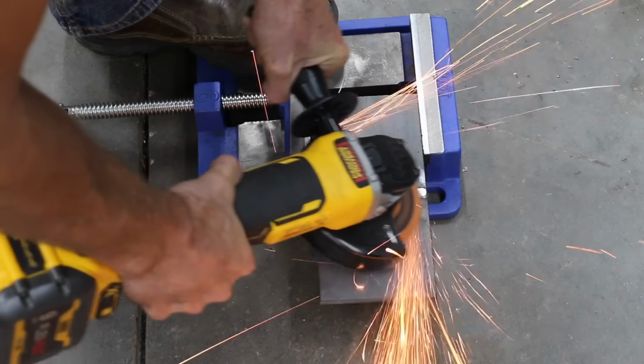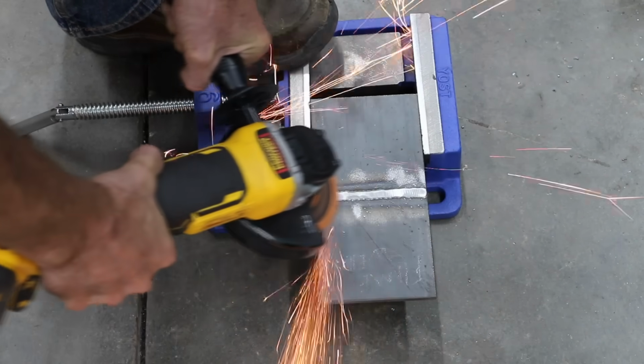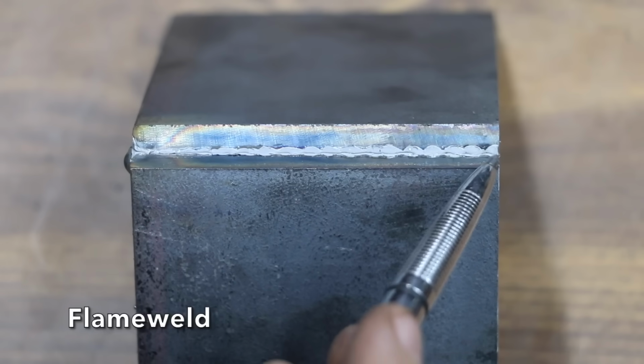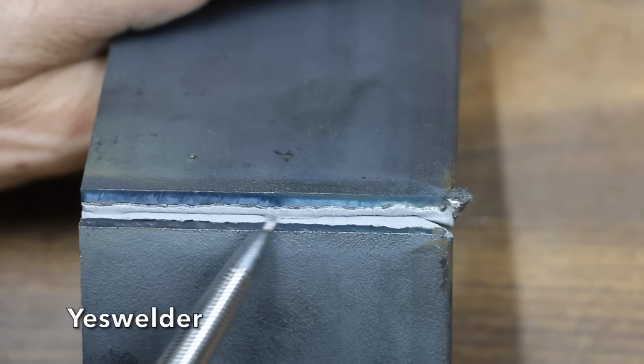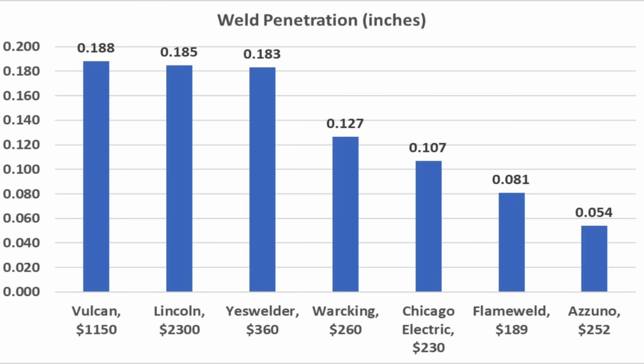I'll go ahead and grind off the weld that's just above the steel plate so we can measure penetration. I folded each of the test pieces and measured the area with the deepest penetration for each of the brands. And the Vulcan delivered the deepest weld at 0.188 inches, but the Lincoln was in a close second at 0.185. The Yeswelder also performed very well at 0.183 inches.